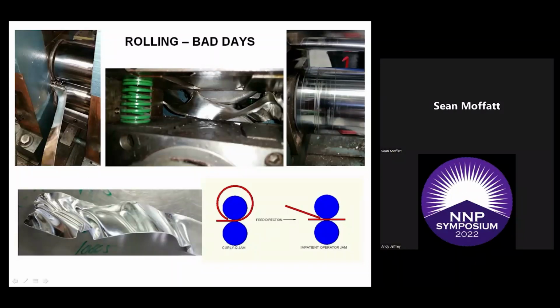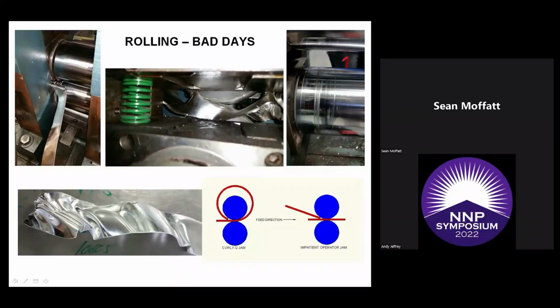And in the same way, if you get a piece of schmutz or yuck that lands on your roll, it's going to sit there and squeeze an image of that garbage into your strip. Interestingly enough, Murphy's Law applies when you do this, and that piece of yuck won't stick to the strip. It'll just stick to the roll. So every time that roll comes back around, it'll press that image back into the strip, and it says stay on the strip just one time, so you can ruin an entire strip by just putting that piece in there. So if you have like a 5-inch diameter roll, about every 16 inches is going to have another impression of that piece of garbage on your strip.